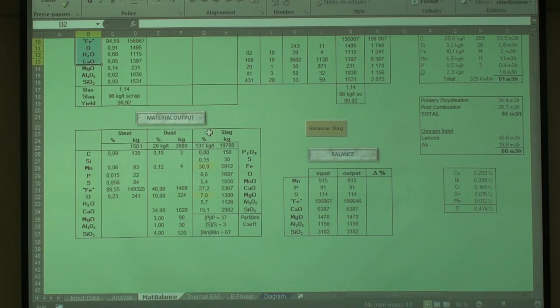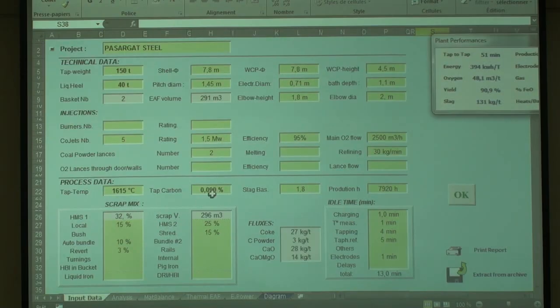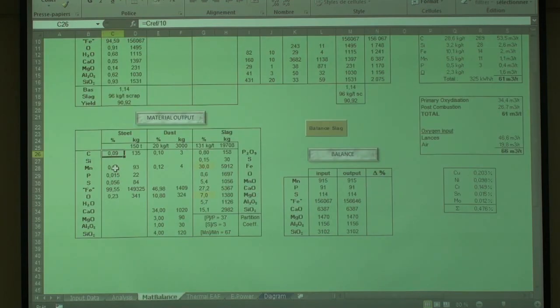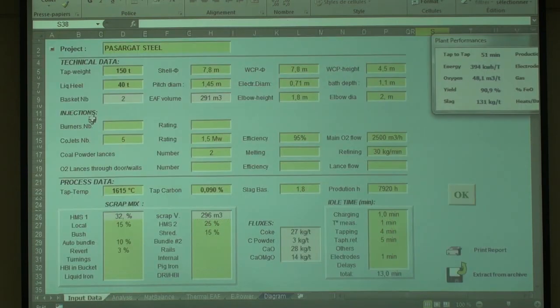Yeah? So we have seen yesterday that the steel analysis is coming from the input data here, carbon at tapping. Then manganese is calculated with this equilibrium, phosphorus and sulfur as well. The Fe is 100 minus the rest of the elements, and the oxygen is given by the thermodynamic equilibrium when the carbon has reached 0.09, and depending on the temperature as well. Yeah? Because this is input data D22. D22 is the tapping temperature.